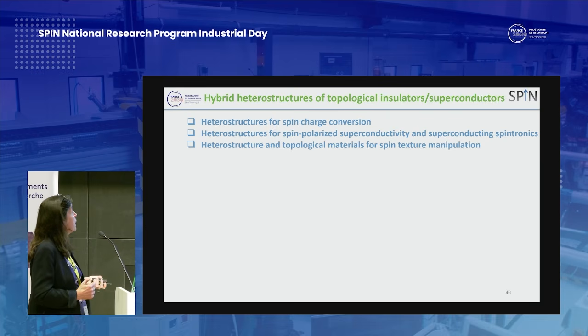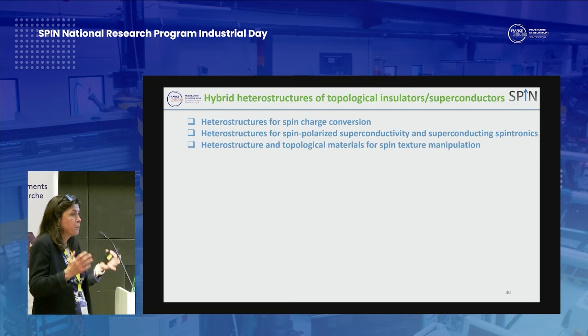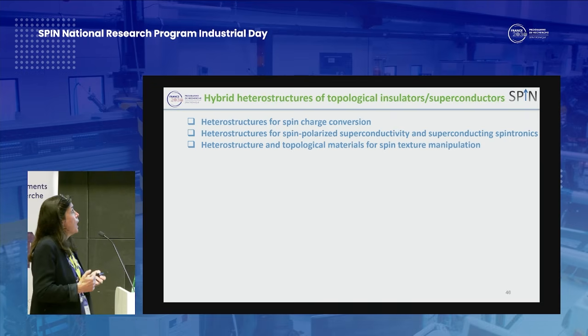The last work package takes advantage of proximity effect and competitive interactions that can emerge from heterostructures in which you've got layers that have a very radically different spin order. For example, a topological insulator with a superconductor or with an antiferromagnet. And in this work package, we aim at the production of heterostructures for spin charge conversion, spin polarized superconductivity, or